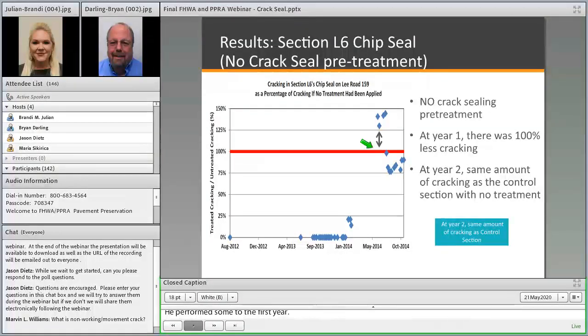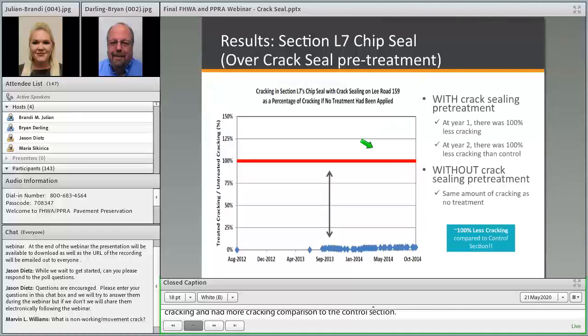But in year 2, when we got into that second winter of 2014, you can see that all of the chip seals started cracking open, and in fact began cracking and had more cracking in comparison to the control section. So basically what this data was telling us was that after about 2 years it loses any value in comparison to having done nothing.